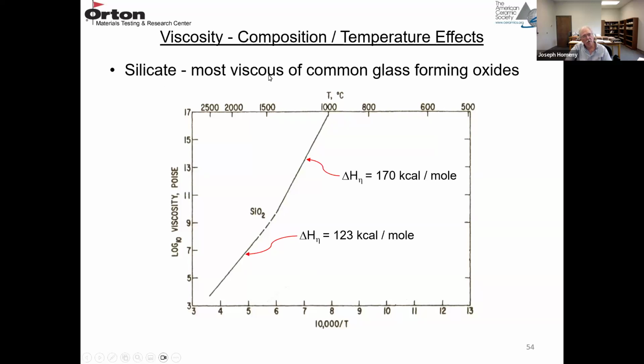Silica is the most viscous of the common glass forming oxides. It has the highest viscosity. So this is a plot of the log of viscosity versus the inverse temperature. This is in poise, this is 10,000 over temperature, but up at the top here is temperature in degrees C. So temperature increases from right to left. And then this is the viscosity curve. So as you increase the temperature, the viscosity decreases.